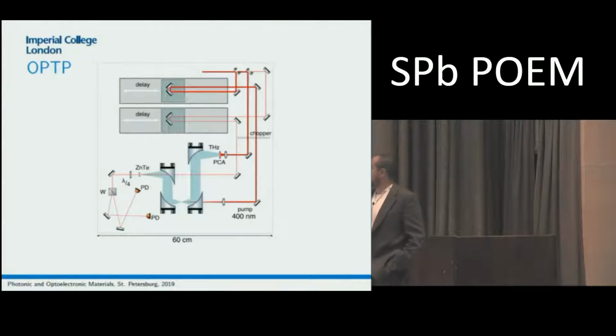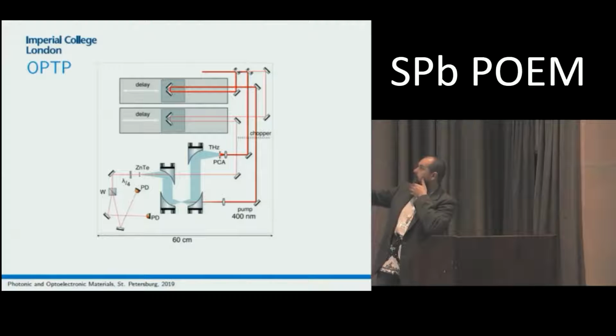This is just the setup, which is a typical optical pump terahertz probe setup. The BBO crystal is missing, but we are pumping with 400 nanometers, which is well in excess of the energy of the band gaps for all the perovskites that we are using. So the beam is split into pump delay and probe delay beams.